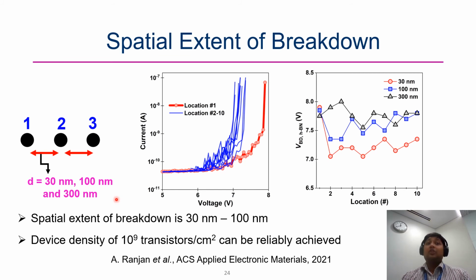And this also tells us that the device density that we can reach with HBN, assuming breakdown as a reliability criterion, can be 10 raised to the power 9 transistors per centimeter square.